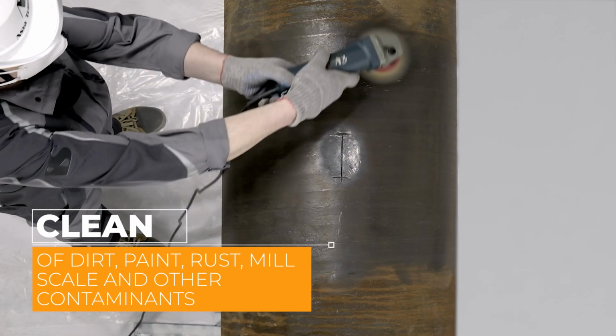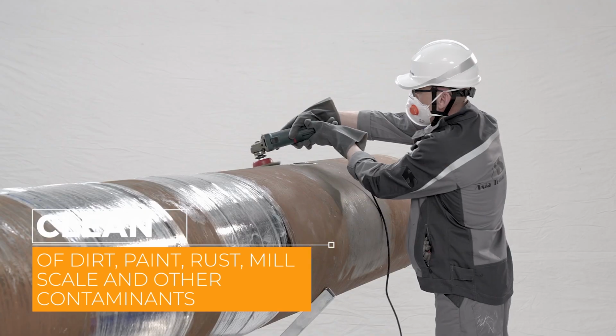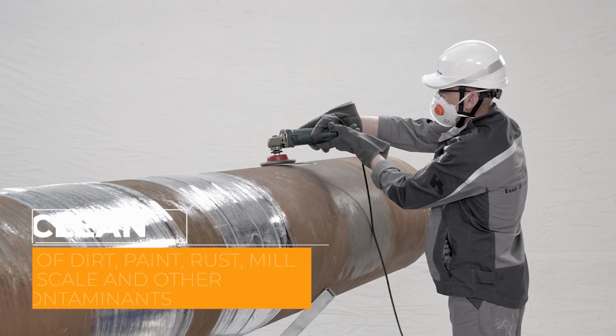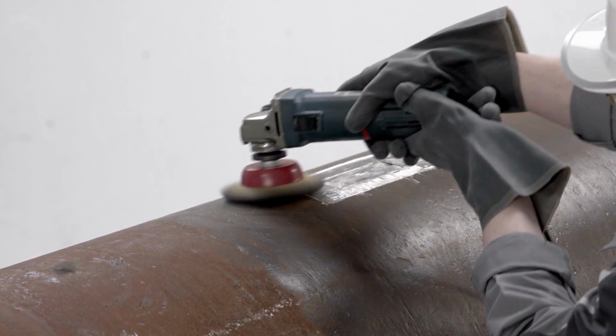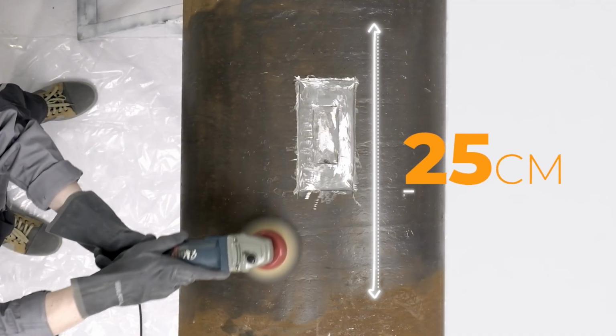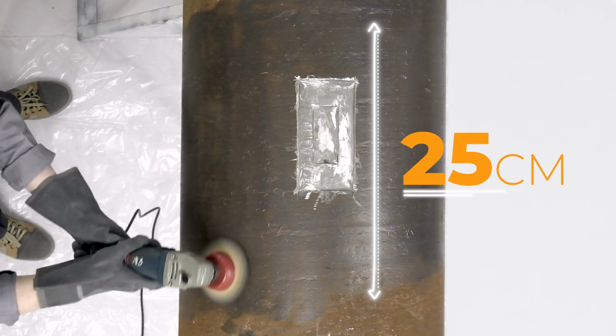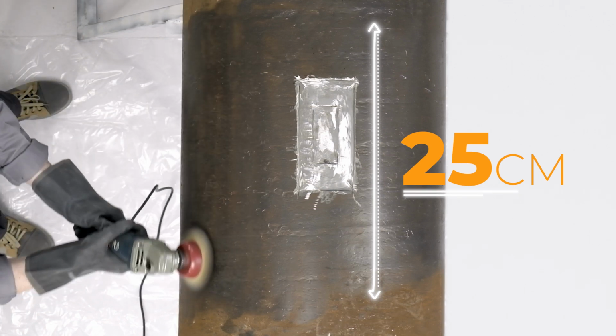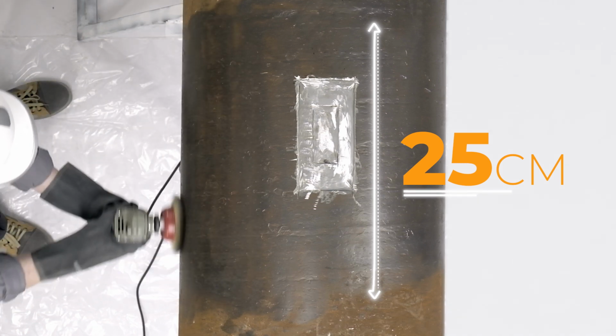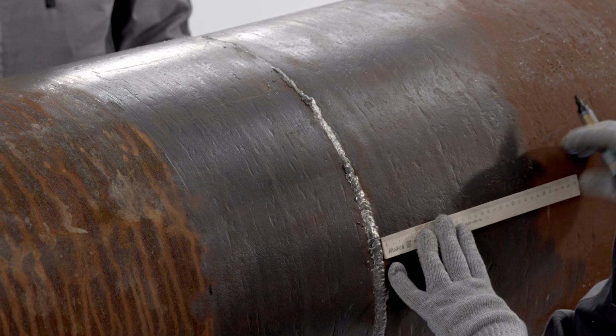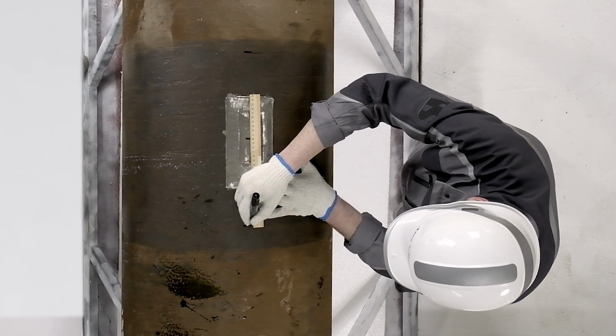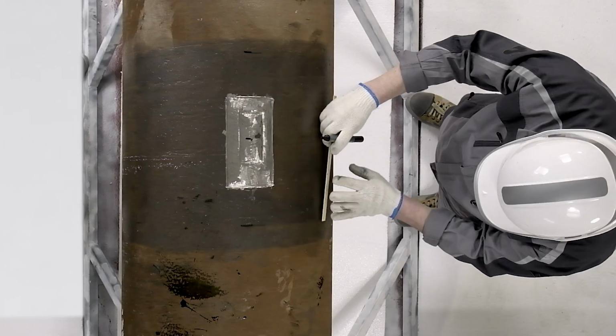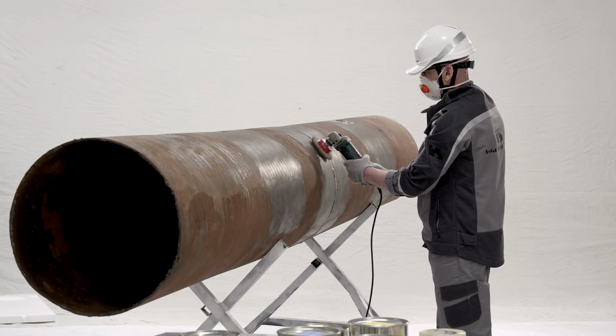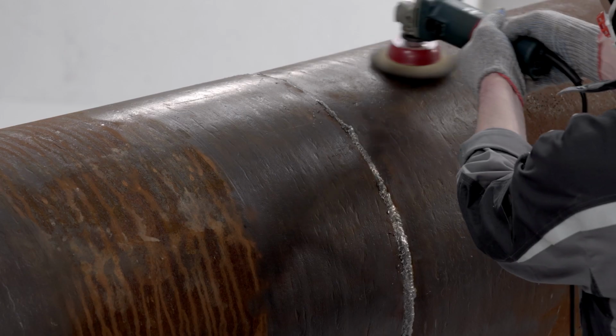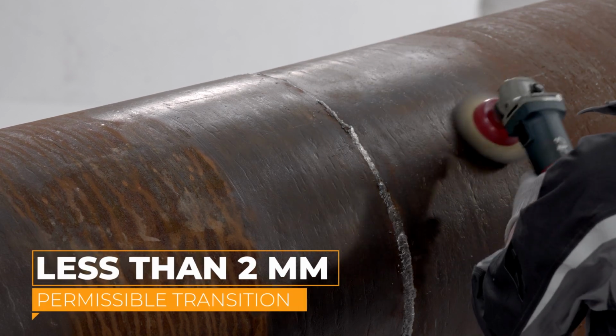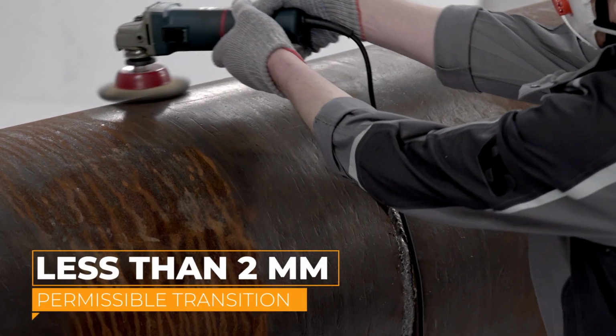The pipe in the place of the installation of the coupling after removing the insulated coating should be cleaned of all dirt, paint, rust, mill scale, and other contaminants, including places of defects. The width of the stripping around the pipe perimeter should exceed the width of the installed couplings by at least 25 centimeters on each side from the center of the defect. The repair area is marked with a marker on both sides of the pipe perimeter. Sharp transitions in defective areas should be smoothed with a grinder. Permitted surface transitions with a radius of curvature of less than 2 mm.